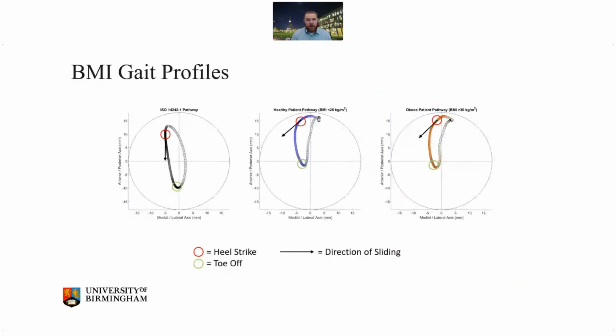When you look at those kinematics and you compare them to the kind of motion profiles that you expect the contact patch to go over on the hip replacement components, the kinematics are also very different. So the sliding distance is different, the sliding location is different. You don't have this kind of nice oval, but you actually have a bit of an abrupt stop and reverse, and then the areas for peak load and directions of sliding are all very different.